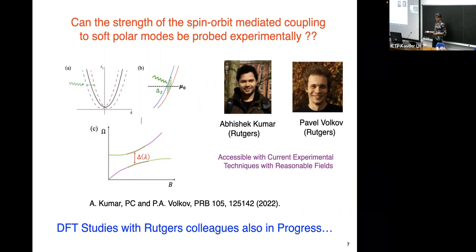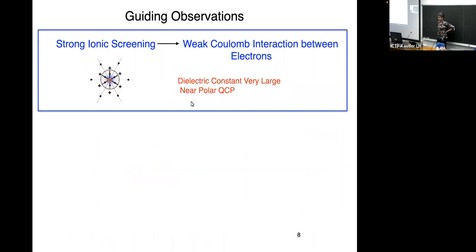I should also say that we're doing DFT studies with our Rutgers colleagues, both to get the strength of the spin orbit coupling and also to get the strength of the two phonon coupling that I'll be talking about. So what are the guiding observations that Piers, Pavel, and I have played into ours? The first thing is that we have very strong ionic screening, so we have very weak Coulomb interactions between the electrons. The dielectric constant is very large near the polar quantum critical point, and we'll see that that means that rs is very small, even though it's dilute.